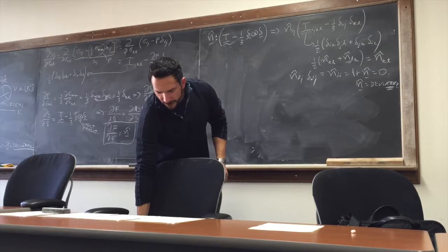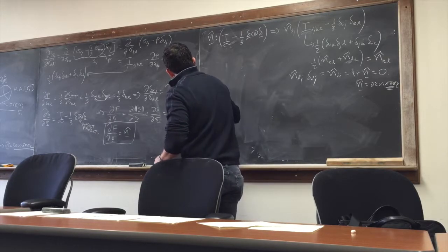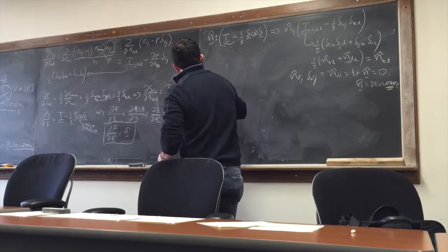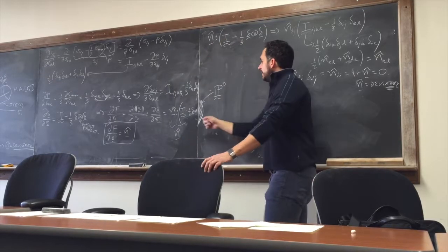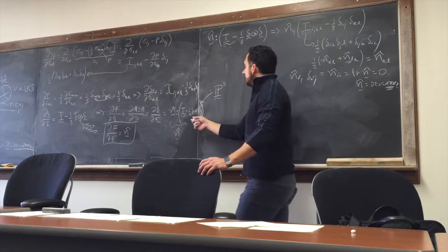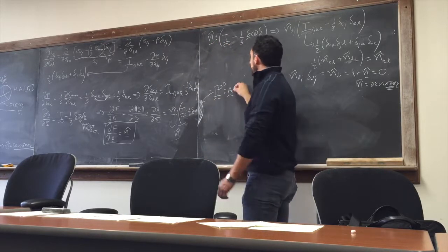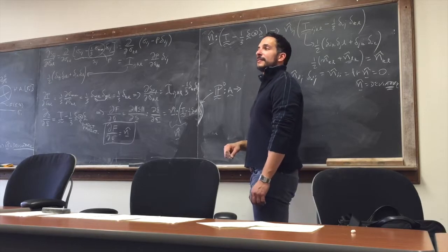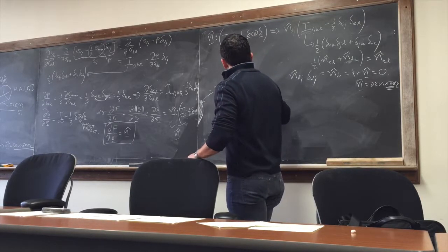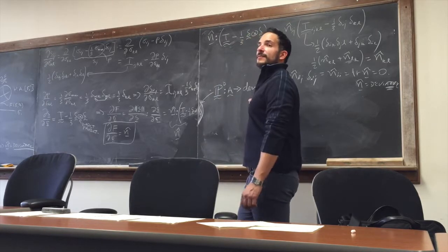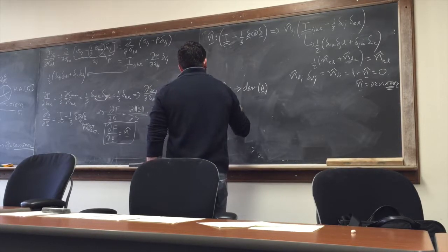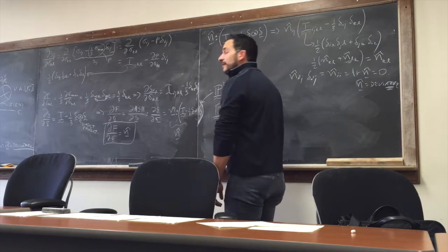Okay. So we're here. This puts us in a position to define what I will many times refer to as the deviatoric projection. It is this fourth order tensor that, when you double contract a second order tensor with it, guess what it gives you back? The deviatoric projection, or the deviatoric component of that same tensor. So if you were to hit sigma with this guy, what do you think you get out? S.